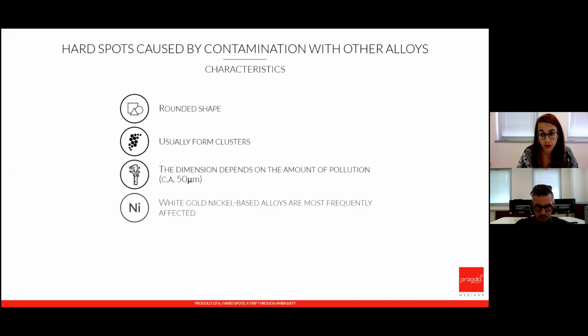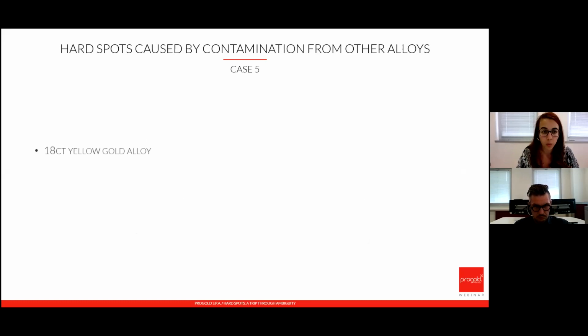We can also have contamination from other alloys, not only from crucibles. In this case, you also have a very rounded shape and they come in clusters. Also, in this case, nickel alloys are usually affected, and it can happen even in the presence of fresh metal. Why does this happen? Well, here we can have three main cases.